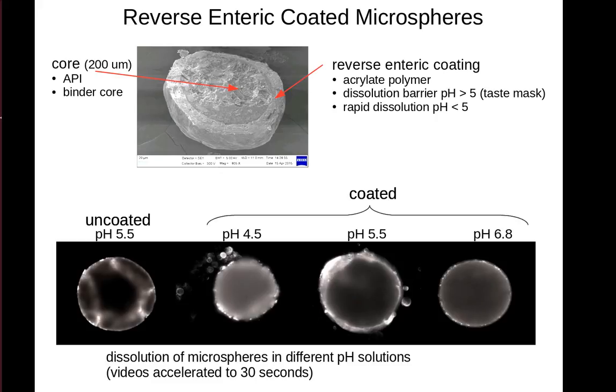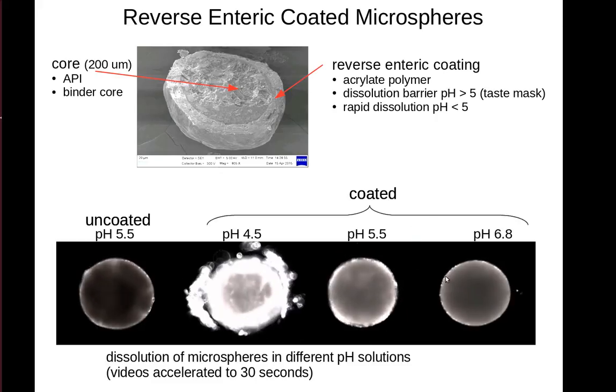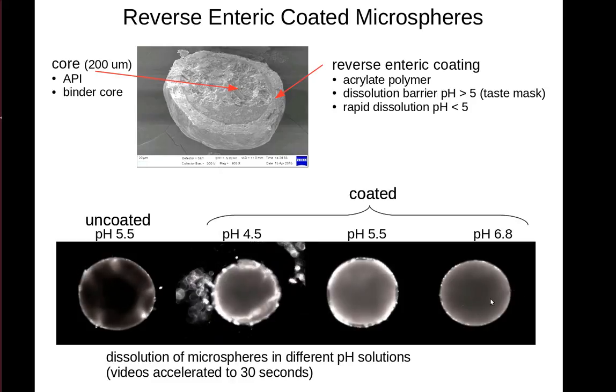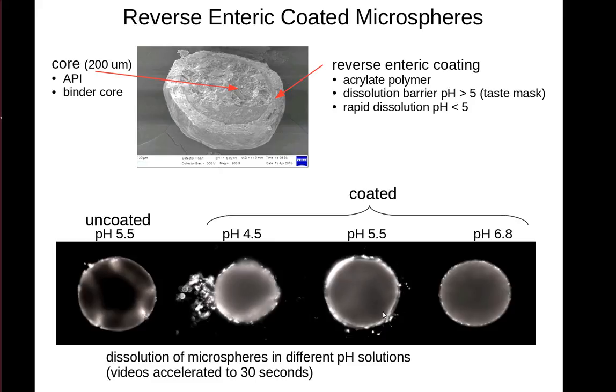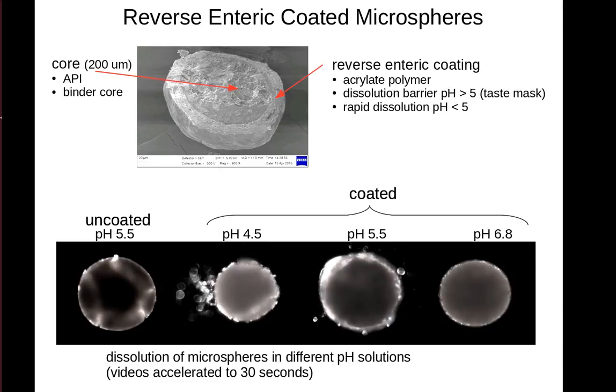Conversely, at 6.8, the mouth conditions, the polymer keeps the core intact and we do not see much dissolution. And at the intermediate pH of 5.5, there's substantial swelling of the polymer, subsequently followed by dissolution, before it swells as much as we'll see from some other polymer types.